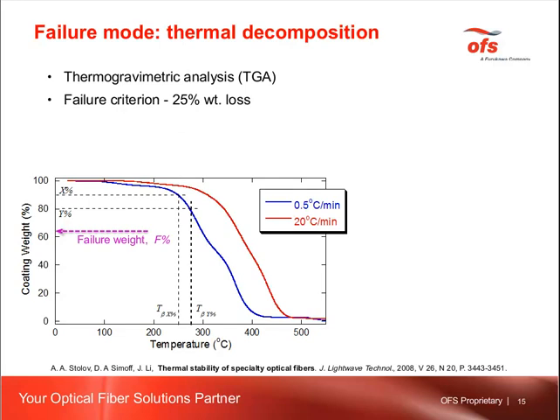First of all, an important failure mode at elevated temperatures is thermal decomposition of the coat. And this can be followed using thermogravimetrical analysis. In this method, a sample is heated from room temperature to some high temperature, and at a certain point we can see that the weight of this sample is getting lower due to thermal decomposition. So we can follow thermal decomposition using thermogravimetry, and the question is, what should we take as a failure criterion?